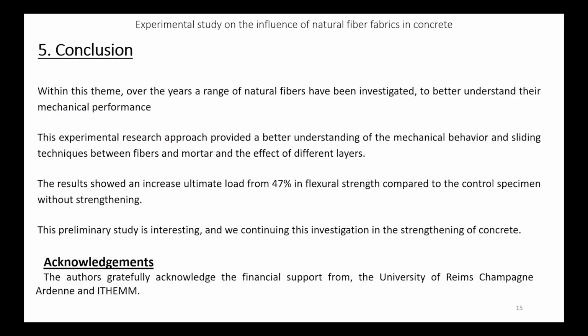So for the conclusion, with this work, a range of natural fibers have been investigated to better understand their mechanical properties. This experimental research approach provides a better understanding of the mechanical behavior and sliding technique between fiber and mortar, and the effect of different layers. The work showed an increased ultimate load of 47% in flexural strength compared to the control specimen without strengthening, and it is not to be ignored.